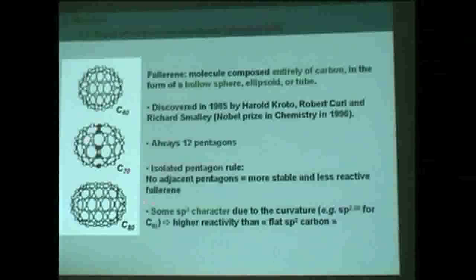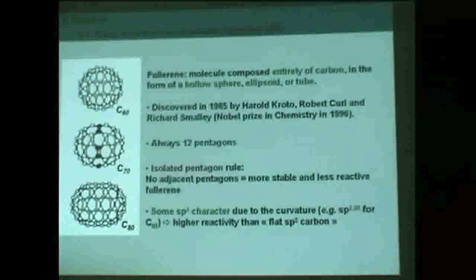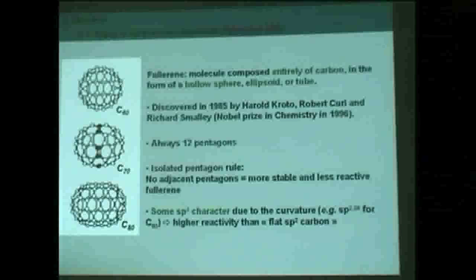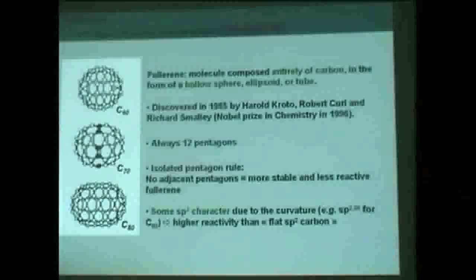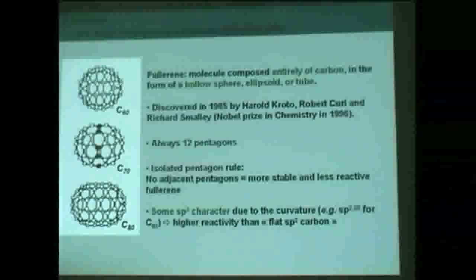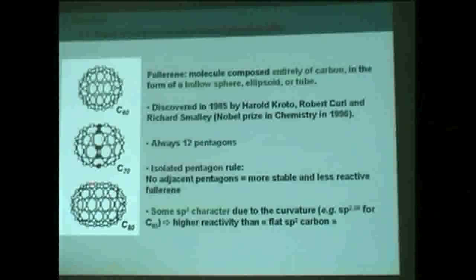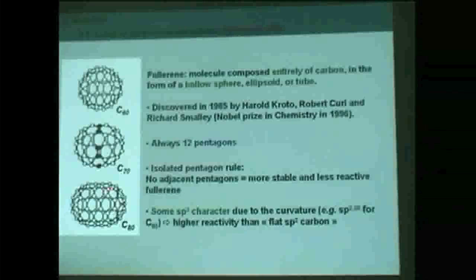Okay, here we've got a lot of pentagons, a lot of local Gaussian curvature, and as a consequence, this is no more flat. If we consider that this type of bonding, the curvature locally, is not only due to sp2 but sp3, we can explain this bonding locally at the atom. It means here we've got something which is not flat. So one way to describe that is to introduce some proportion of sp3 in those.